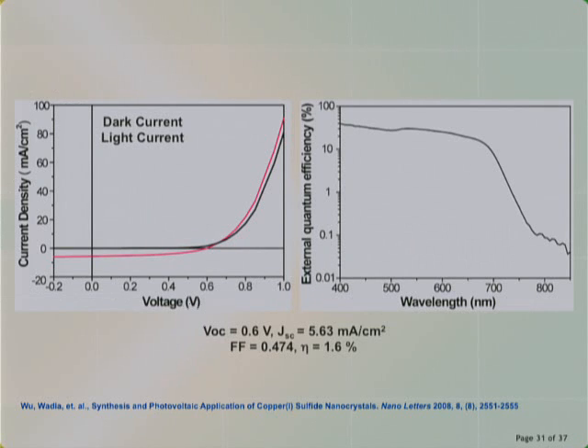Now, this is the standard IV curve to talk about how efficient your solar cell is. I'll just talk about these numbers. Our open circuit voltage, 0.6 volts, is actually quite a good number. It's what we would have expected for the band gaps we were working in. This is the number that concerns me, the 5.6 milliamps per centimeter squared. It's very low, and as a result, we have a modest efficiency, 1.6%.